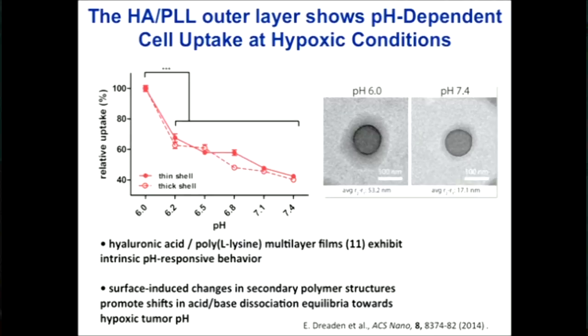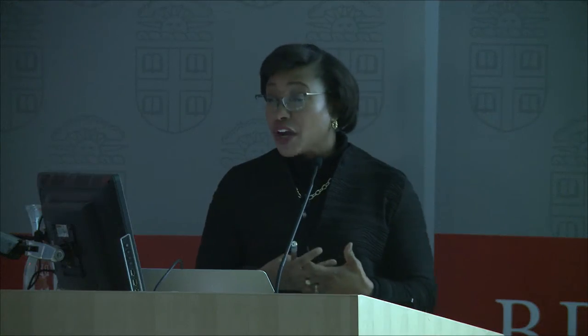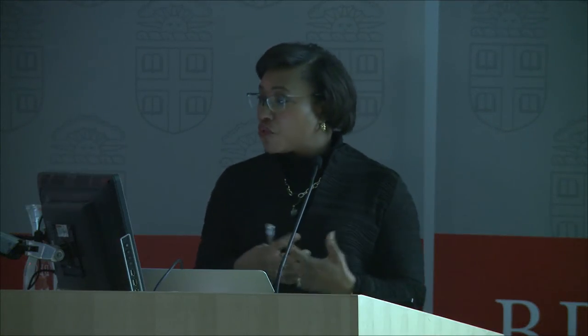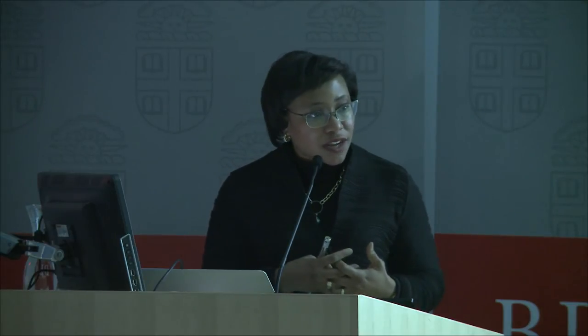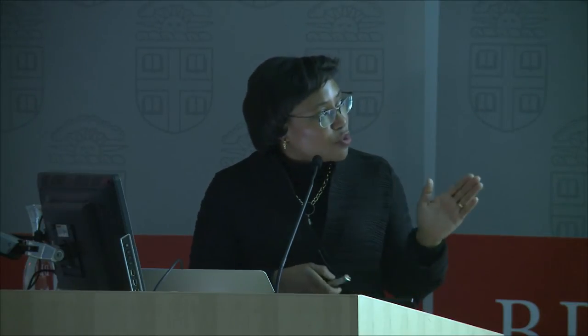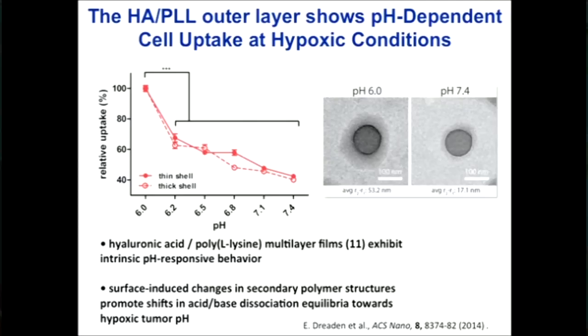It turns out that these polyelectrolyte multilayers are nanoscale blends, and they actually can express isoelectric points that correspond to the two groups that are expressed by these polyelectrolytes. That means that at a certain point, it can flip from negative to positive. And what we see here is that it's on its way. It's becoming near neutral. Some measurements, we see a slight positive charge. It's got a softer, mushier shell, and the cell actually takes up much more of that.